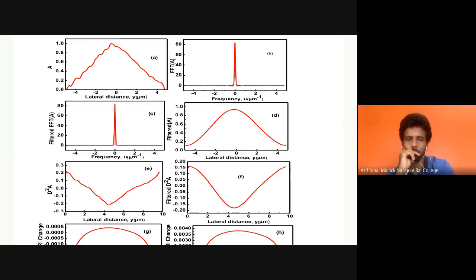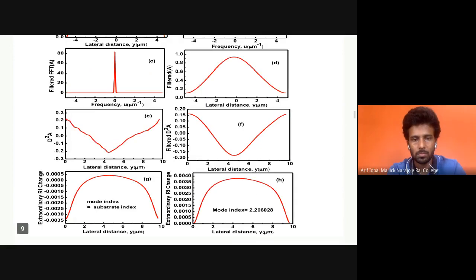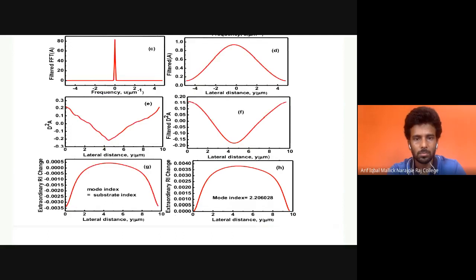We get filtered A, but a small noise presence in the amplitude profile will tremendously increase in its double derivative. So we have to eliminate the noise in its double derivative also. We follow the same procedure and obtain the refractive index change profile in figure G. But we observe that the refractive index change is negative, which is unexpected.